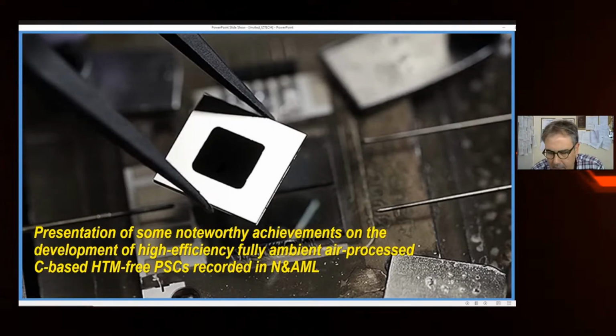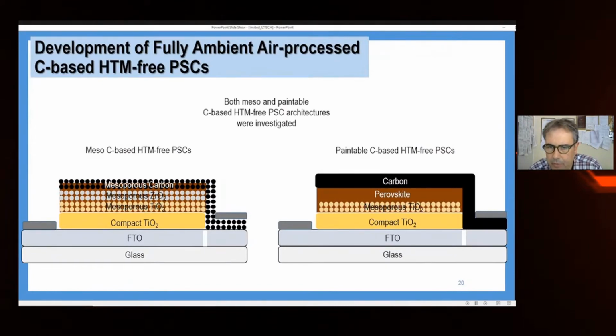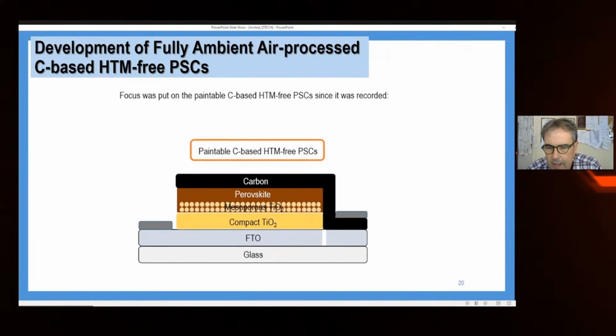Now I'm going to present some achievements that we have made here, and I want to share with you. As I said, we started with both of these structures, the mesoporous structure of perovskite solar cell, and of course this paintable structure, which is finally our choice. The important thing, as I said before, and I repeat it here, is that we don't have any HTM material. It means that there is no organic material in the space between the perovskite and the positive electrode. So it is very important because this is, of course, something that causes some problems after taking accelerated tests to see the stability of the devices. And finally, this is cost effective because these materials are really very expensive.